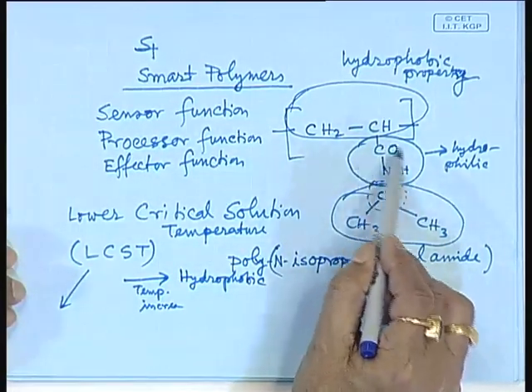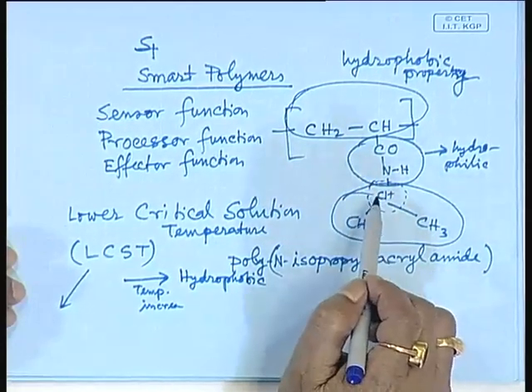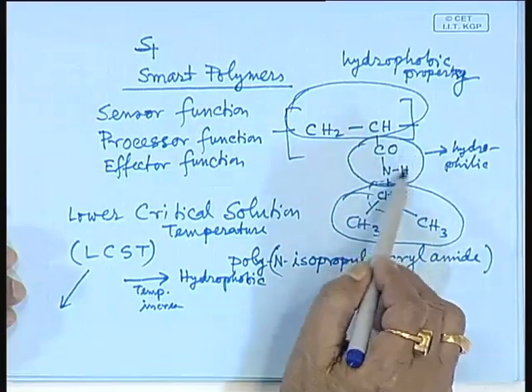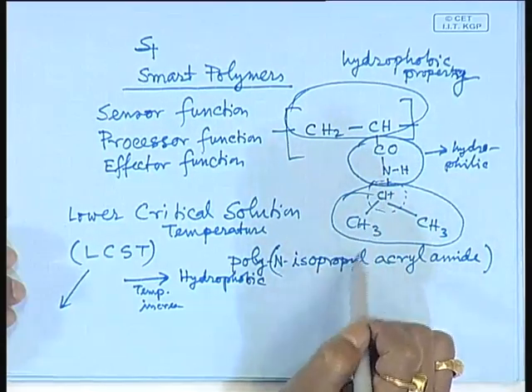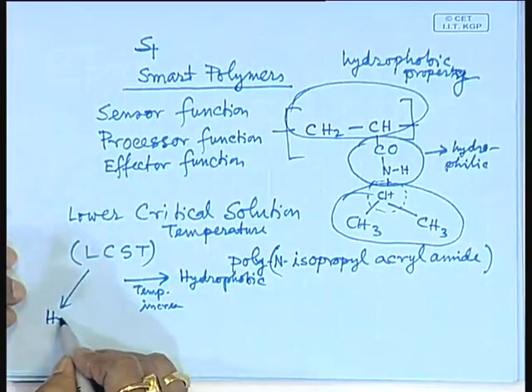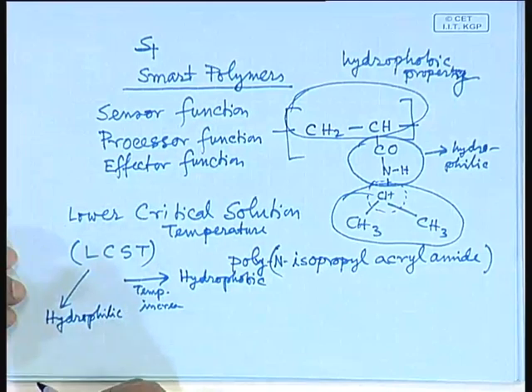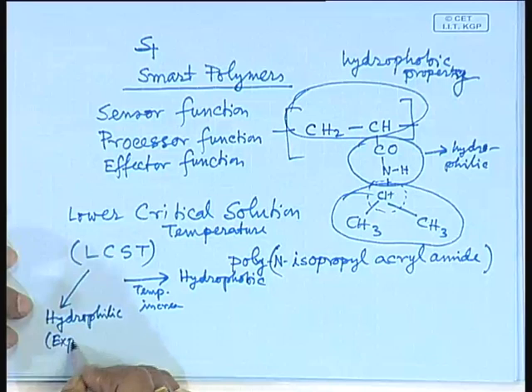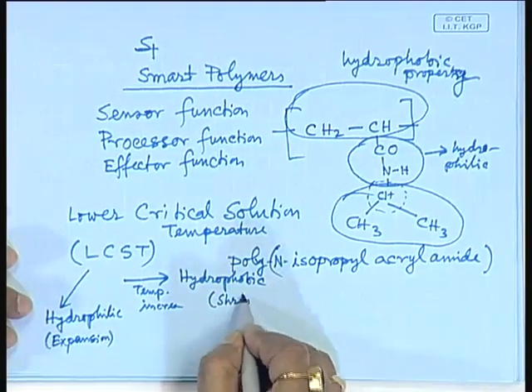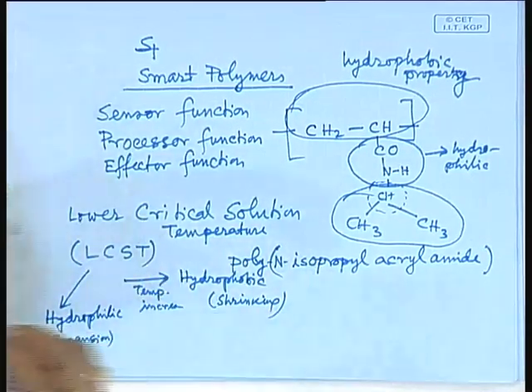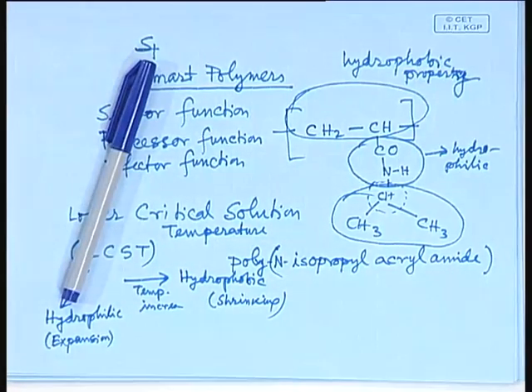That means, in order to make this polymer hydrophilic, this portion should be exposed. Again, if you want to make this portion of the polymer molecule exposed, it should expand. It shows expansion, it shows shrinking. So, the polymer either shrinks or expands. Shrinking due to assumption of hydrophobic configuration, okay, and expansion or swelling due to hydrophilic configuration. Swelling, you see, it is very simple, it is not very difficult.